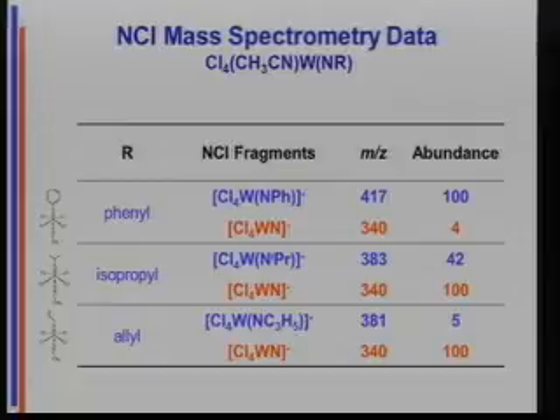I get 4% cleavage. With the isopropyl, where I now have secondary alkyl to nitrogen from my bond cleavage, all of a sudden the terminal nitride is the base peak, and I see about 42% still there. And then allyl, where I've weakened that bond another 15 kcal per mole, the base peak is still the terminal nitride, but I see only 5% of the intact allyl amido. So I know that, at least under the gas phase ion conditions, I can break that bond I need to break to do the deposition.